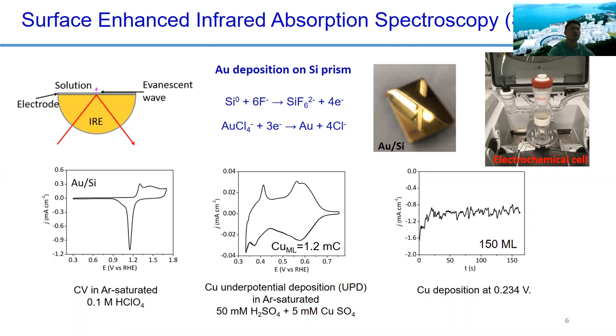There are two advantages. One is that there will not be too much water absorption. Second, the signal of reaction intermediates on the metal surface will be amplified. Okay. So what we do is we use a reflective element, typically silicon, and then on the silicon surface we deposit a thin metal film, for example platinum or gold. It's a working electrode.